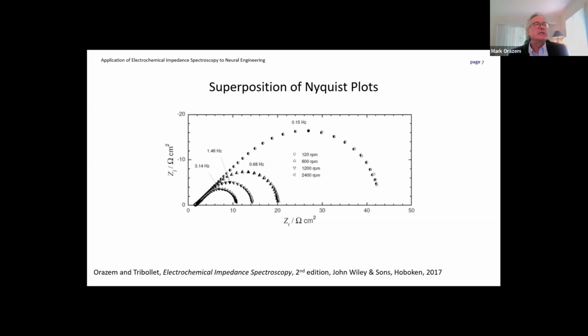And so I'd like to show you three examples of that. The first one is for reduction of ferricyanide on a platinum rotating disk electrode. These are different rotation speeds, multiple measurements taken at different rotation speeds. And what we see is that as the rotation speed changes, the impedance changes in magnitude.